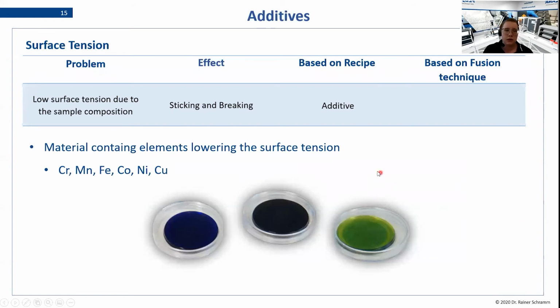The problem with the surface tension can also come up due to the sample composition. There we have the same effect. The bead is sticking, the bead is breaking, the bead is very flat. And here we can only handle the problem by using an additive like a non-wetting agent. So these elements, chromium, manganese, iron, cobalt, nickel, copper, those are the elements and components of samples that do these nice colors, but also cause low surface tension and then sticking and breaking. So if you're dealing with these kinds of elements in your fusion, you for sure from a certain concentration will need some additive there.